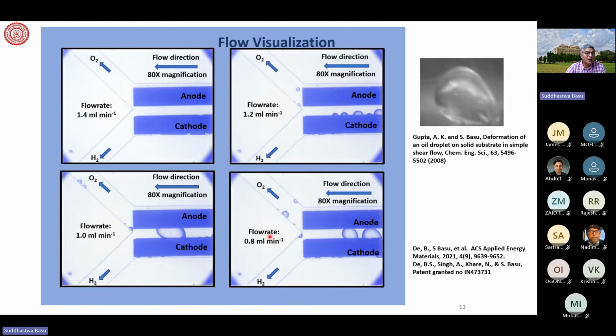You can see that if I have a very low flow rate, the bubbles are growing and not detaching because the shear rate is not very high. And in the process, there is mixing taking place between the anodic channel and cathodic channel. If I increase the flow rate to 1, 1.2, 1.4, the hydrogen bubbles and oxygen bubbles are forming, but the flow rate is high and they don't intermix. Because of the high flow rate, the shear rate is high, and the small droplet that is forming detaches and goes along with the streams, with no possibility of intermixing.